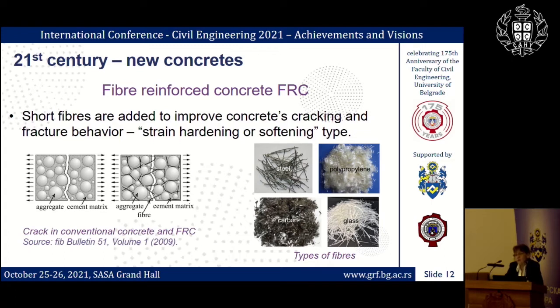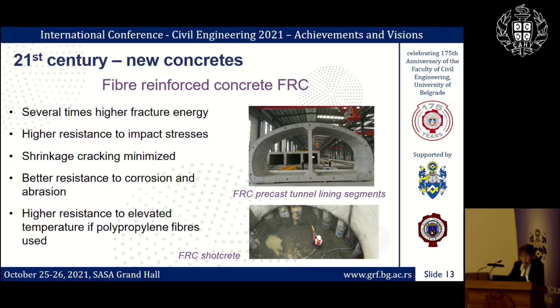So fibers enable reduced cracking, generate post-cracking residual tensile strength with relatively large tensile strain, and in that way turn the brittle behavior of concrete into, let's say, strain hardening or strain softening type. We use usually steel, carbon, glass, plastic fibers for fiber-reinforced concrete. Natural organic fibers are also used, but they have an aging problem, and care should be taken when they are used for structural concrete. Some properties that are improved with this type of concrete you can see here.